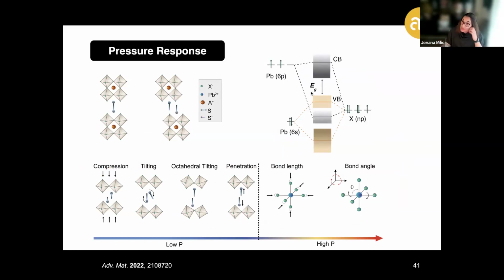This has been previously demonstrated on a number of occasions, which however involves relatively high pressures above around 5 gigapascals or even towards 10 gigapascals, which leads to beneficial changes such as reducing the band gap or even metallization of these systems, but which often leads to changes that are irreversible and also, with such high pressures, not very practical for functional device applications.